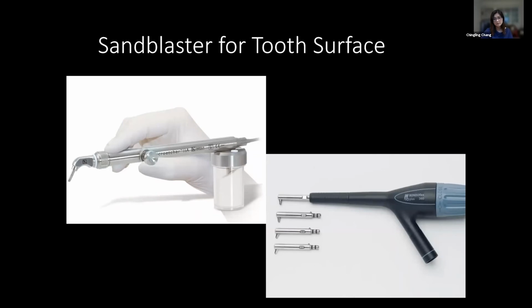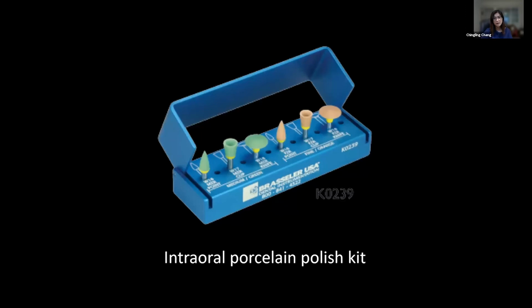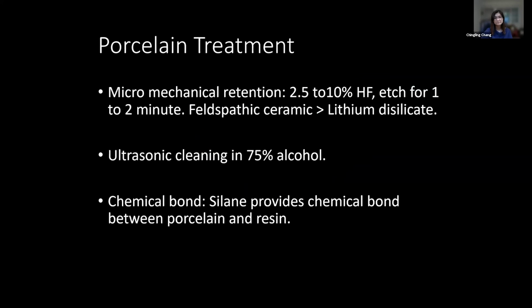This is a sandblast I use before cementation only. I use it to clean the tooth surface. And you also require a porcelain polish kit because there are a lot of adjustments after you do cementation. So you will need to polish the porcelain surface after you cement the onlay.